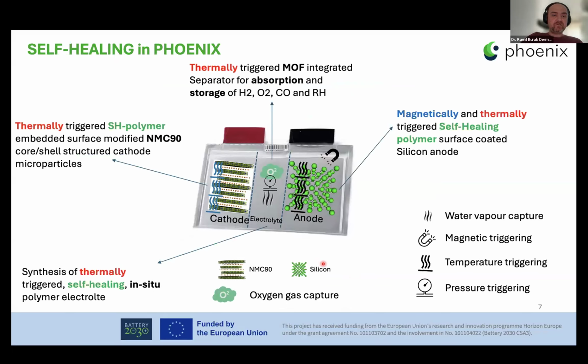So in that concept, for the self-healing part in PHOENIX, as I said, we have various types of functionalities considered in a single cell. For example, from the cathode side, we have thermally triggered self-healing polymer embedded surface modified core shell structure cathode particles. So we simply coat the cathode active materials with the thermally triggered self-healing polymers.